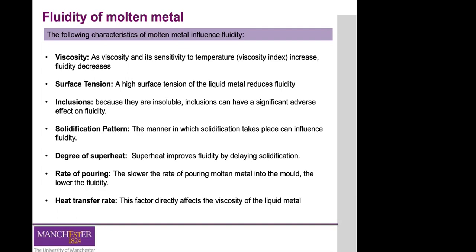The degree of superheat is defined as the increment of temperature of an alloy above its melting temperature. The more temperature we provide above the melting point — the higher the degree of superheat — the higher will be the fluidity, because we are delaying the solidification process. The pouring temperature is often specified instead of the degree of superheat, simply because it's easier to specify.